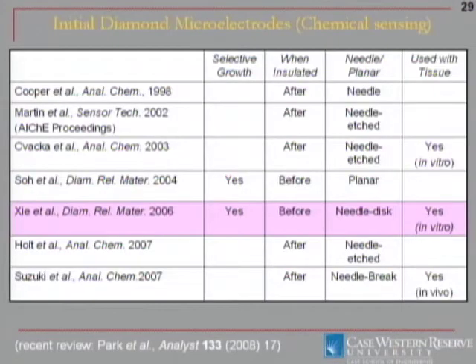One of the reasons we haven't gotten farther with the tissue measurements is because of the limitation in using those microdisc electrodes, because they break. And this is not unusual. Here's my electrodes I was showing you, and we did do some in vitro measurements. This is most of the literature out there on making diamond microelectrodes, and most of them have made them in a similar way of making needle electrodes, and very few have been able to be used in tissue.